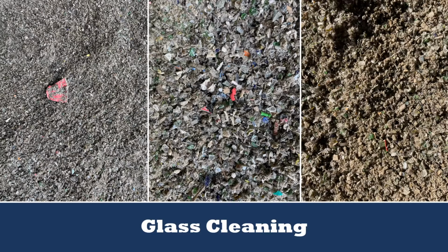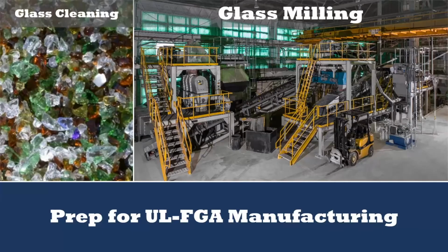All right, and the way that we do that is everything's dry. We're not using any type of effluent or wet process anywhere. We're using a lot of screens. We have several magnets in the system, vacuums, dryers, those sorts of things. But generally, it's a completely dry process, and we're trying to get the glass as dry as possible during this process as well. All right, so at the end of cleaning, we hope that the glass looks as clean as what I'm showing in this left-hand photo. At the end of the cleaning process, we should be left with a majority of just glass.